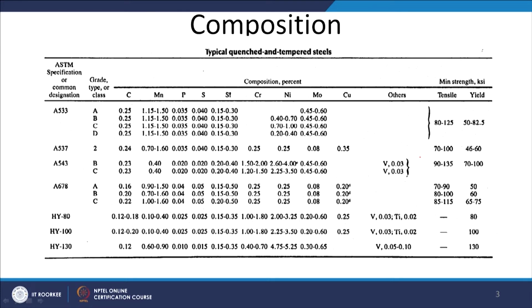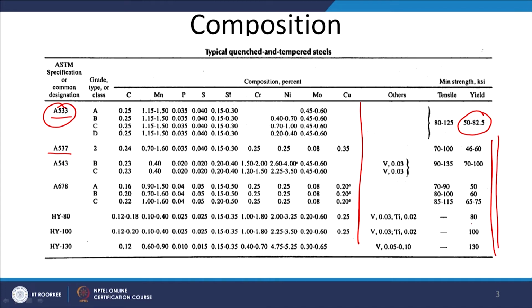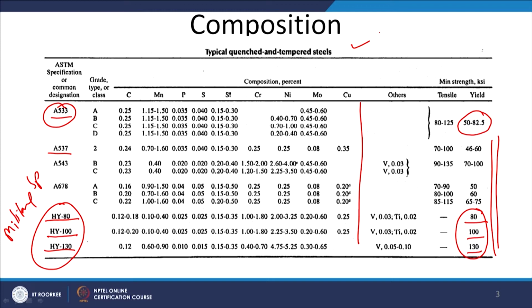There are other categories of Q&T steels like A533, A537, and each one has its own composition and tensile strength. A533 steel has a lower yield strength as compared to 517 or 514, with a yield strength range of 50 to 82, and likewise others also have lower yield strength except these three. HY80 has a minimum 80 KSI yield strength, HY100 has a minimum 100 KSI yield strength, and HY130 has 130 KSI yield strength. These are specially designed and covered under military specifications, while other grades are covered under ASTM specifications. All these are commonly used Q&T category steels.